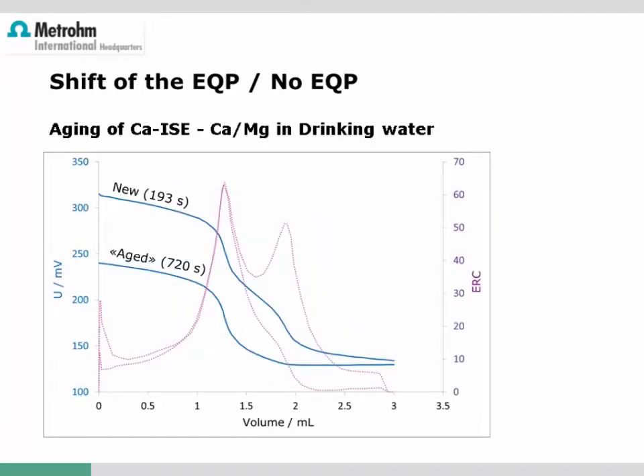This effect can also be seen for polymer membrane electrodes like the calcium ISE. The expected lifetime of such an electrode is usually up to 1 year, and the difference in performance can be seen in the following example, which is the titration of calcium and magnesium in drinking water. The new electrode enables a clear separation of the calcium and the magnesium. The ERC has 2 clear peaks, especially for the magnesium. With little more than 3 minutes, the total titration duration is also reasonably fast.